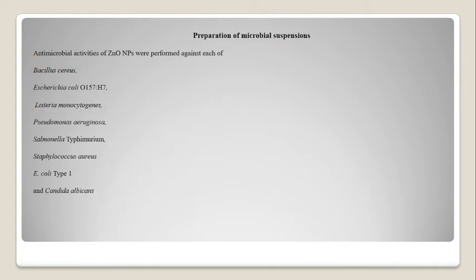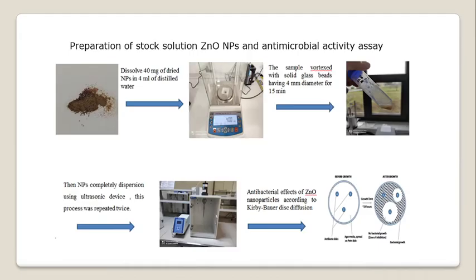Preparation of microbial suspension. Eight microorganisms were used, most of them bacteria, including gram-positive and gram-negative bacteria. Preparation of stock solution of zinc oxide nanoparticles and antimicrobial activity assay. 40 mg of dried nanoparticles were dissolved in 4 ml of distilled water. After that, vortex for 15 minutes. After vortex, the dispersion of nanoparticles using an ultrasonic device. After that, the evaluation of antimicrobial activity of nanoparticles using the disk diffusion method.